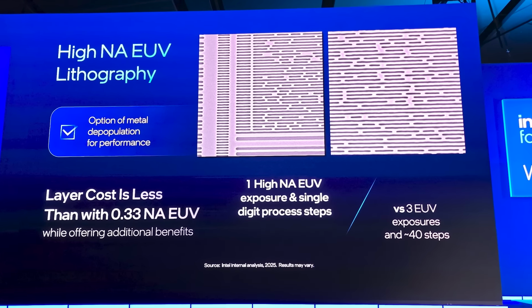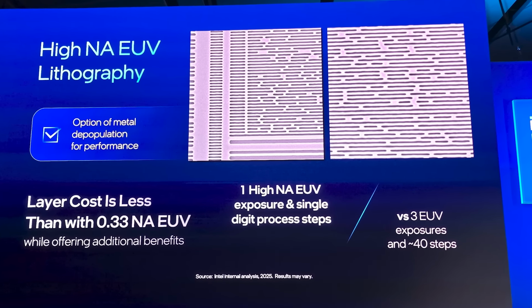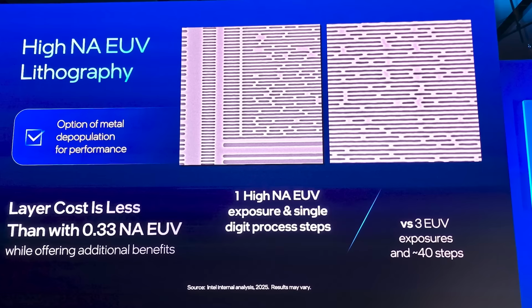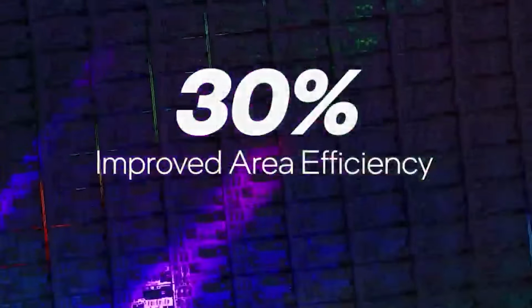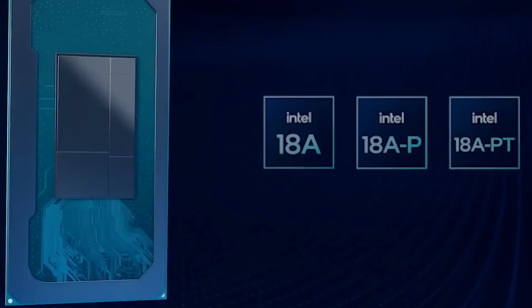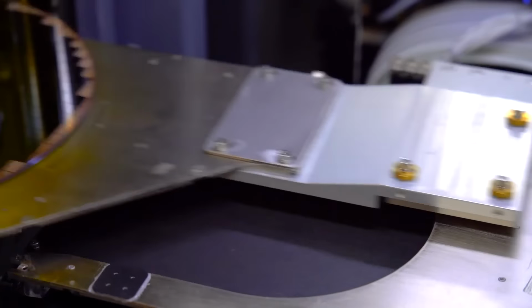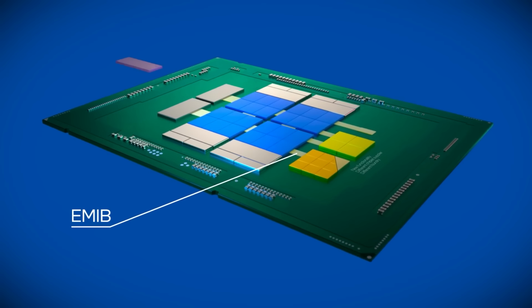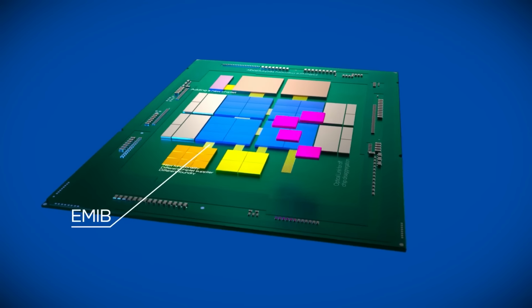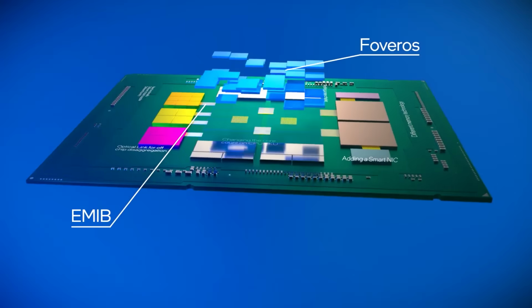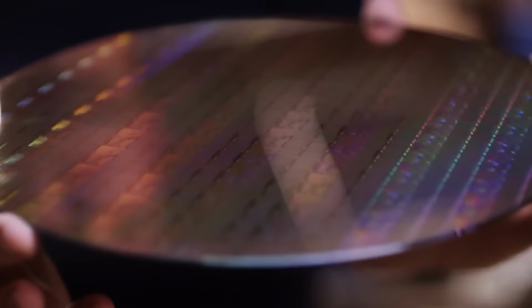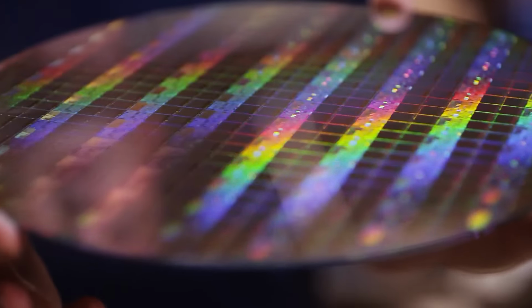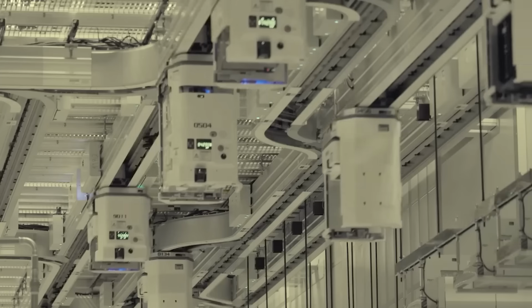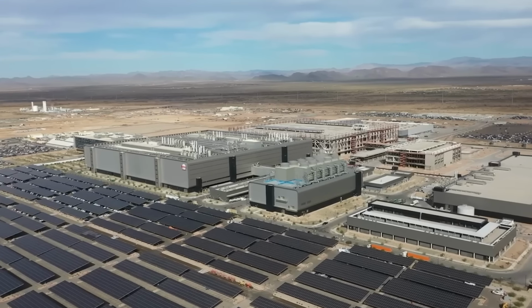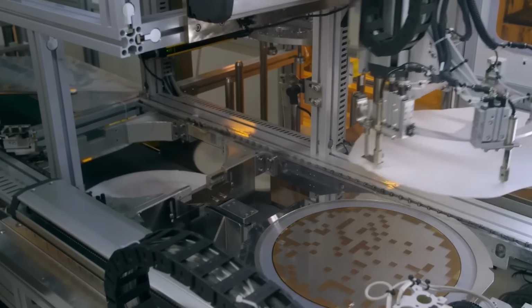The logic makes sense when you look at the economics. High-NA single exposure by itself is more expensive than double patterning with standard low-NA EUV. The throughput penalty from the smaller field size is real, but pair High-NA with DSA and the equation changes. DSA can rectify EUV printed guide patterns and define the finest features within a process that is largely self-correcting. You reduce the number of exposures needed, lower defect rates, and improve yield, and Intel has already shown substantial yield improvements on low-pitch metal and via layers by incorporating DSA into the patterning flow.